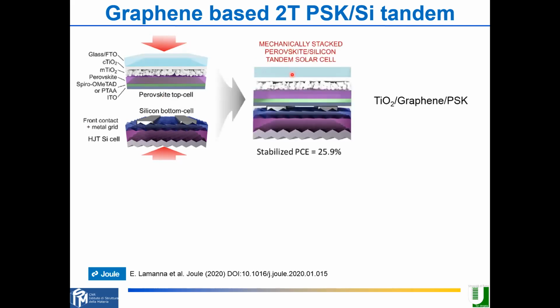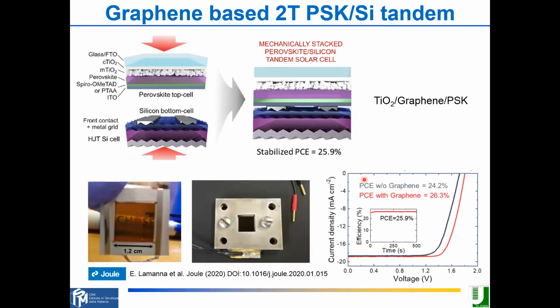So you push one on the top of the other. So it's a sort of wafer bonding. So we were doing this, and then we were using also 2D materials to improve the efficiency. So this is the top perovskite solar cell. This is the silicon, mechanically stacked solar cell. And this is the final efficiency. So we were able to push the efficiency from 24.2% up to 26.3% by using graphene in the titania.